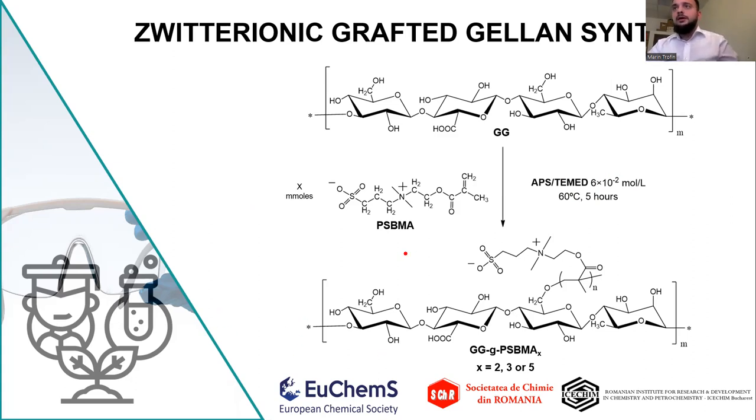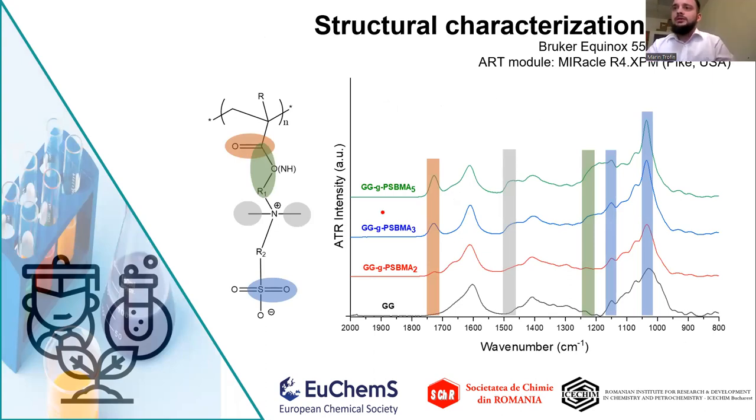By FTIR, we see some differences compared to pure gellan, and because we used three different amounts of sulfobetaine methacrylate monomer, higher and higher amounts, this is confirmed by specific peaks, such as the methacrylate one from the ester group, also the one from the carbon-hydrogen group, from the newly introduced methyl and methylene groups. And also we see an increase in these bands, which is due to the presence of the